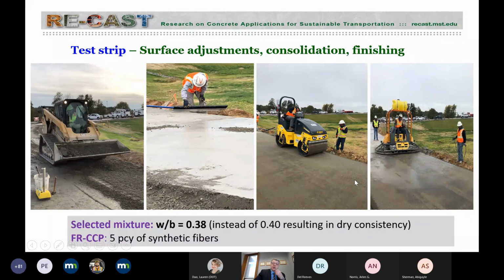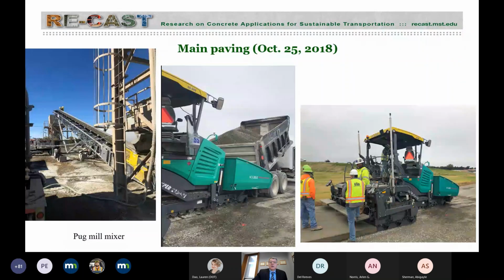And finally, the mixture was adjusted, going down from the 0.4 w/c with 6 pounds per cubic yard to mixture number 4, which is 0.38 with 5 pounds per cubic yard. All in all, that's a mixture that gave us better performance. So the next day we moved into the actual placement of the 3 cells.